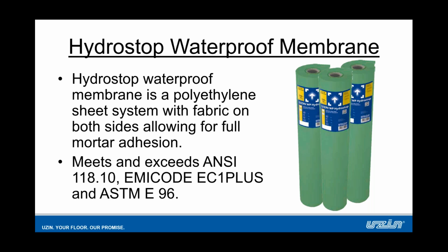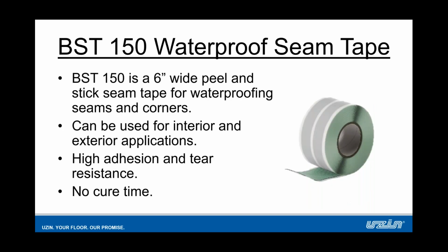But then we're exceeding expectations with our breaking strength. The 118.10 calls out for 170 pounds. We're at 865 pounds breaking strength. It calls out for 8 pounds of seam strength, and we're at 48 pounds with seam strength. So we're exceeding that standard. The final standard there is the EMICODE EC1 Plus. This is measuring emissions in products. We're at 0 VOCs, and the EC1 Plus is the highest standard that can be achieved, and we're at zero VOCs with that product. So we have a high performing waterproof membrane here that goes beyond residential showers into commercial steam showers.